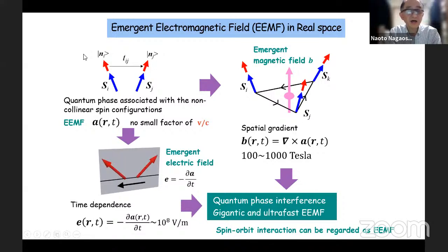Okay, so this non-collinear spin structure leads to the vector potential, small a. So this is the same vector potential as we discussed for cuprates. The important point here is that once you have a coupling between the conduction electrons and spin direction, namely once you have a strong Hund's coupling between the local spin and the conduction electrons, then this hopping amplitude is associated with a phase factor, which is small a. And this coupling constant does not include the small factor of velocity over the velocity of light. Velocity of electron v is usually orders of magnitude smaller than the velocity of light.